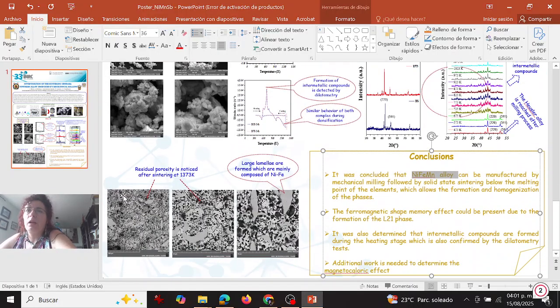And if we have a look at other images obtained with the electron microscopy, we can see that residual porosity is noticed after sintering at 1373 Kelvin. In here and in here we can see the porosity. And if we have a look at this electron microscopy image, we can observe some large lamellae are formed, and are mainly composed of nickel and iron. This large lamellae. All right.